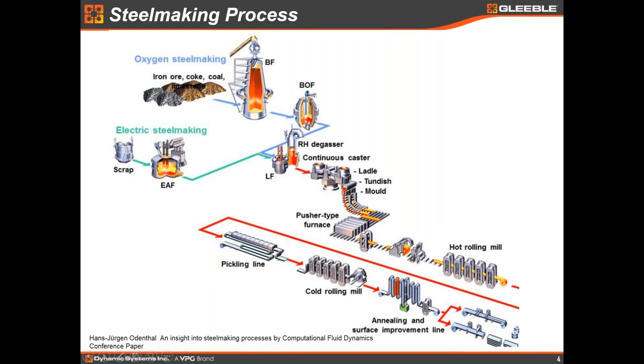The key point about the ladle metallurgy furnace is its significant capacity — it could be 50, 100, or 150 tons. When dealing downstream with the continuous annealing line, I have more than one coil — probably six or seven coils of a given alloy chemistry from any one melt. So if I have an order for only one coil of a particular product but I've melted six coils, that leaves me with five orphan coils that I have to figure out what to do with. Strip annealing simulation gives me an opportunity to figure out processing to convert those excess coils into a sellable prime or high-value secondary product.